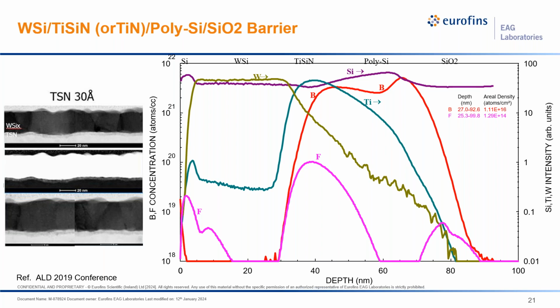So where the fluorine shows up, if it's actually in the silicide nitride layer, and so on and so forth, as well as the boron being identified in whichever layer we detected it. So that is the power of using the multiple modes to be able to give us all the signals on one plot.